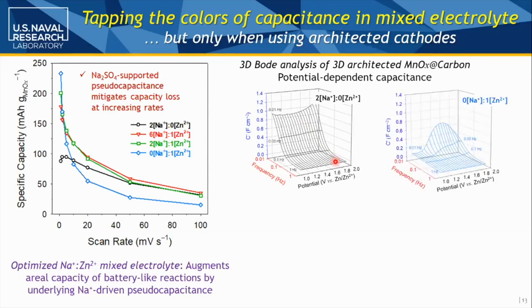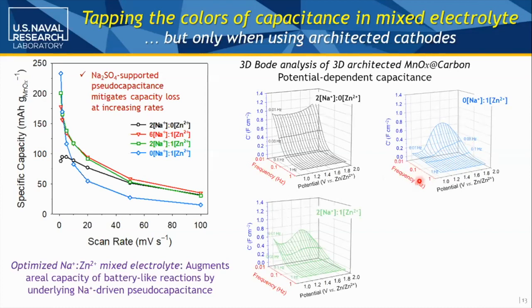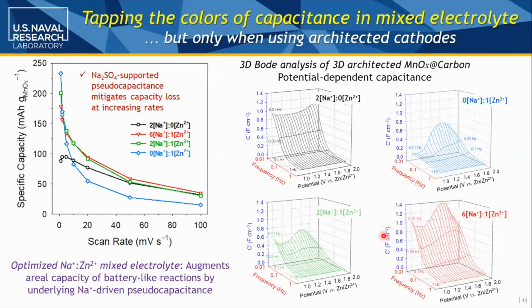Now we're going to look at all zinc. Here's the 0.01 hertz. Again, you can see we're getting less in terms of real capacitance out of this system. And we get that feature that we would want to assign as a Faradaic response. So it is not as, shall we say, electron communicative, even at these slower rates, relative to the pure capacitive response. Here's the 2:1. And here's our preferred one.